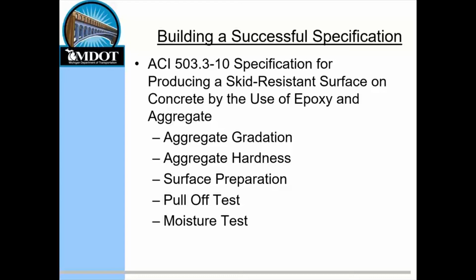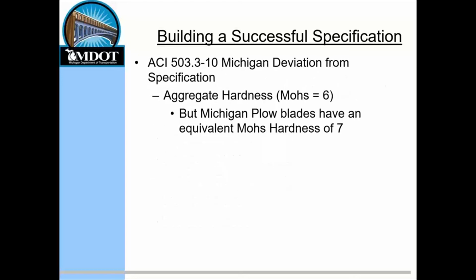Our specification follows closely the ACI 503.3 specification for producing skid-resistant surfaces on concrete. The next couple of slides, though, will show you how we have tweaked that specification a little bit to fit Michigan's needs and guarantee the 20-year life. Our first deviation: most specifications call for a Mohs hardness of the aggregate of 6. Our Michigan plow blades have an equivalent Mohs hardness of 7. We call for a 7 minimum Mohs hardness on our aggregate in our specification to slow down the polishing of our aggregates.